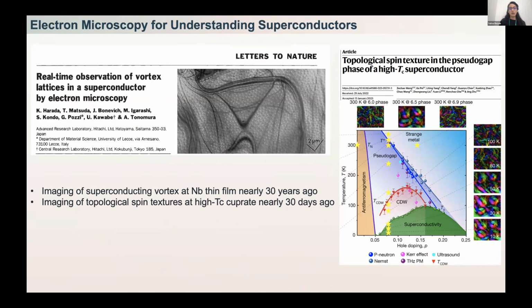Electron microscopy in the past has been tried to understand superconducting states of materials, but this was very limited because we have limited options to perform our experiments, and going down to the superconducting critical temperature is very challenging. But there have been studies, for example one done almost 30 years ago, which for the first time showed the vortices in a niobium thin film using Lorentz TEM. And almost 30 days ago, there was another study that showed the evolution of topological spin textures from the strange metal phase to the pseudogap, charge density wave, and down to the superconducting state of this cuprate.